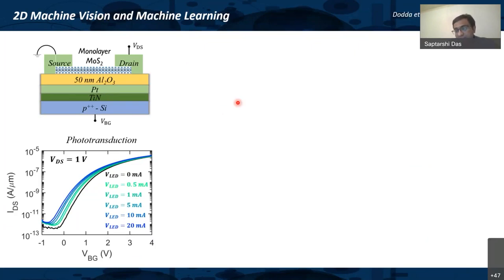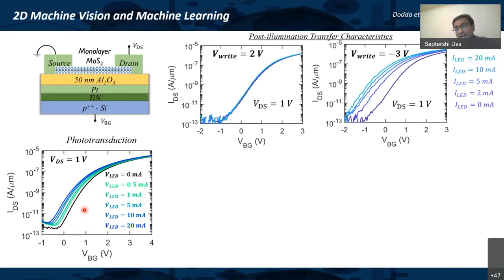And therefore, you have to have a device which is photoactive. The monolayer MoS2 has this unique property that when you shine light on it, the device characteristics change because it is photoresponsive. Now, another important aspect is that when you illuminate this material with light, you generate electron-hole pairs, and some of these holes are captured in the alumina layer. And once you capture these holes, that acts like a fixed charge and changes the threshold voltage of